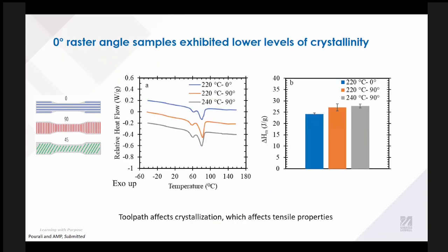We think that some of what's happening in the 0-degree systems is probably related to some toolpath related welding issues, where we're also seeing that the 0-degree raster samples have somewhat lower levels of crystallinity. And so the toolpath is affecting our crystallization, which is affecting the tensile properties in these systems.